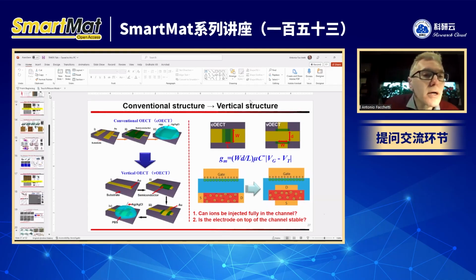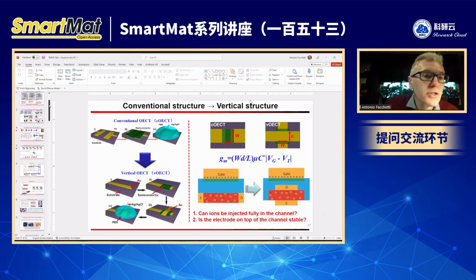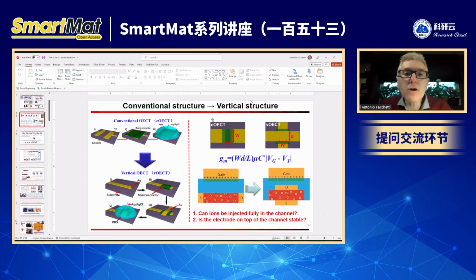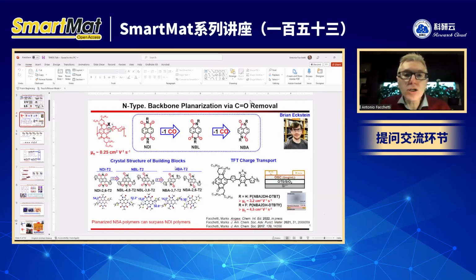Let me see if I can go back. It's actually a very acute question as well. I move the chat on the side. Okay, so this is a very good question. Obviously you remove carbonyl, right? So if you remove carbonyl, your LUMO energy starts going up. So you made the polymer more planar, but at the same time, CO groups are strongly electron withdrawing, right? You remove them, and the energy level for this unit is on the order of -4. And if you go to this unit, you are on the order of 3.4, 3.5, roughly. So the LUMO goes up.